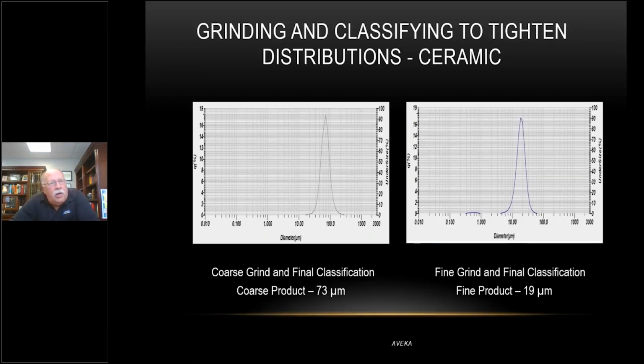Now, you might ask the question, why didn't we grind at a higher particle size so we could get more product out of here? Because obviously we're cutting on the one edge of the particle size distribution. And the reason that we did this is with abrasives, you don't want a lot of large particles. So what you're going to do is get rid of the large particles, cut your yield down a little bit, and end up with a tight distribution like this.